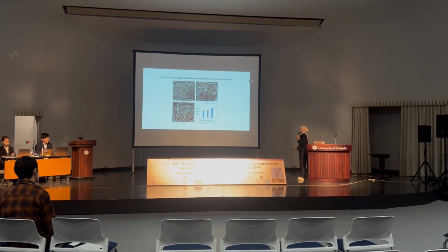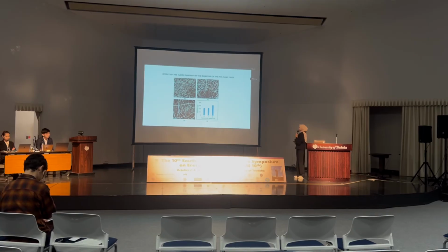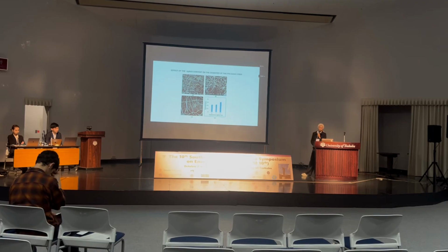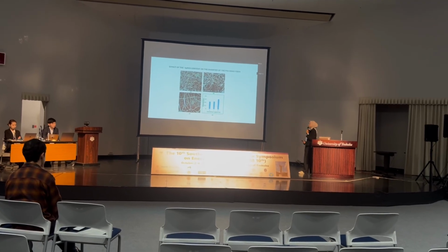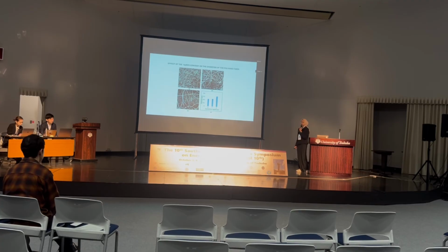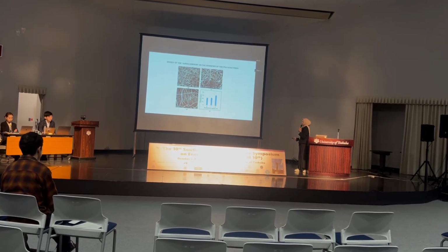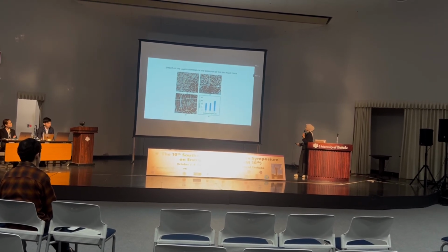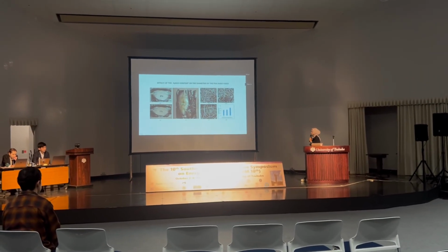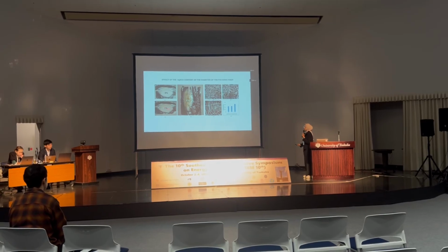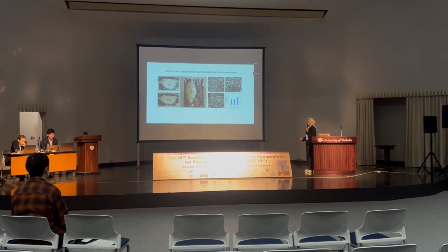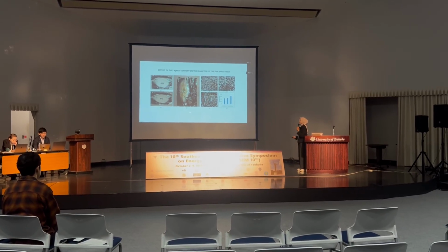I also investigate the effect of the silver nitrate content in the PVA nanofiber on the diameter. The results show that by increasing the silver nitrate from 0 to 1%, the diameter slightly increased, while increasing further to 2%, the diameter sharply increased. The photograph of the nanofiber mat also shows a different color when the silver nitrate is more. The yellowish color indicates that the silver nitrate exists inside the nanofiber.